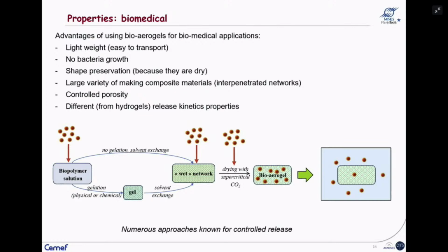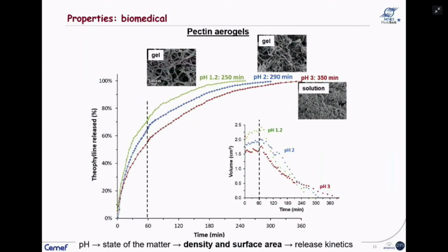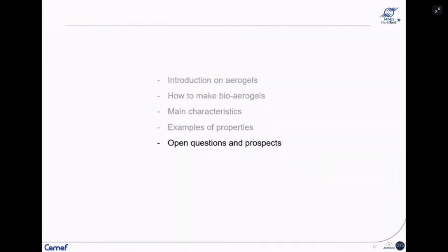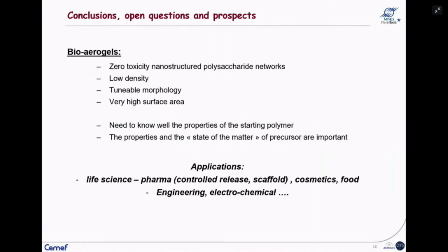And then this drug will be released in different ways, depending on whether your matrix, your aerogel, is soluble in the conditions or not. So this is just an example that, again, with pectin aerogels, you can vary the starting conditions, you can vary network morphology, you can then vary the density, and here is plotted the theophylline release as a function of time, and it is different depending on aerogel properties and the solubility kinetics of the dissolution of the matrix. I think I'm running out of time, and I will finish with the conclusions, and then we will go to the open questions.